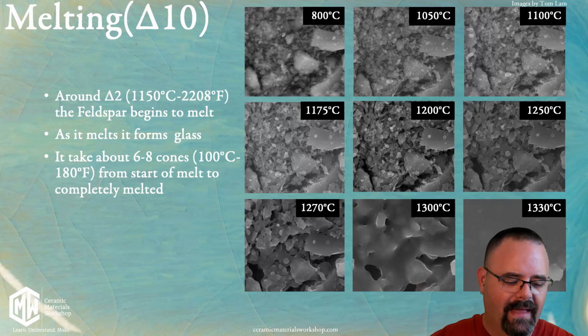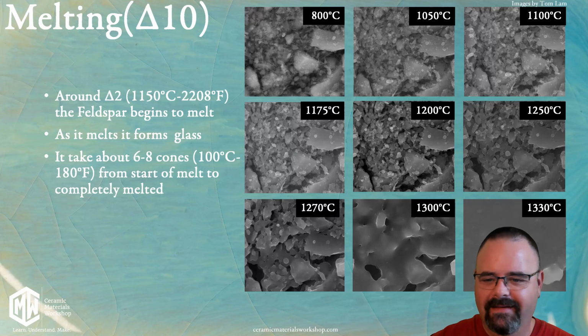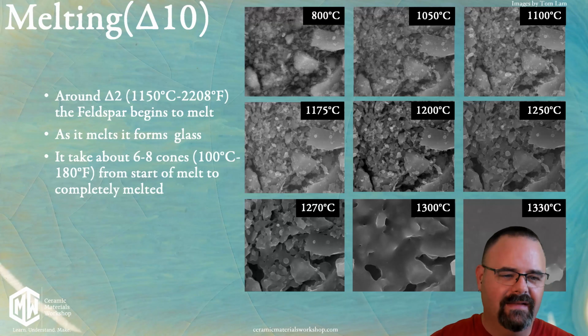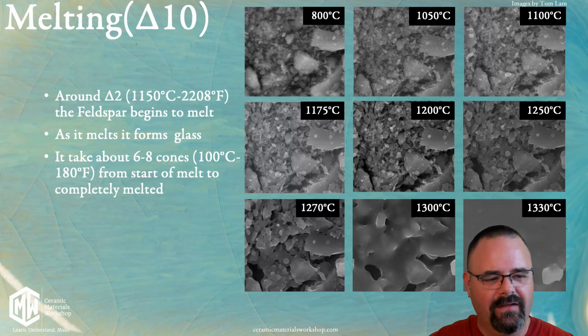And under the SEM, a glaze doesn't look like anything. There's nothing to see in the microscope. But this is a really important detail because it does show that nothing really happens in our glaze until the last 100 degrees C of the firing, about 1230 to 1330 in this case.